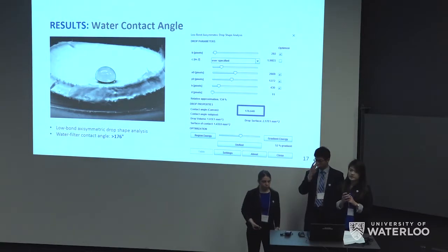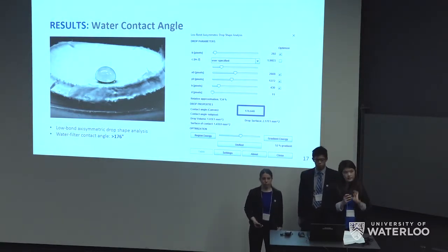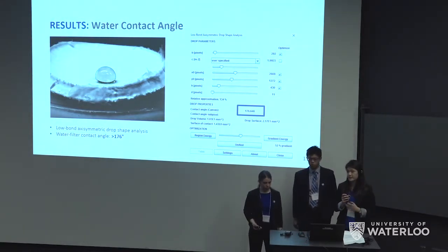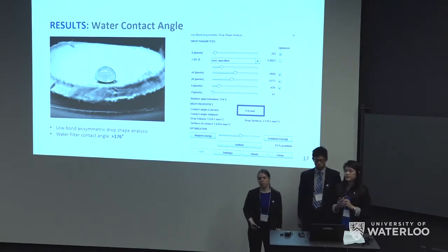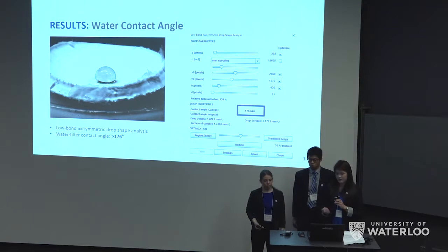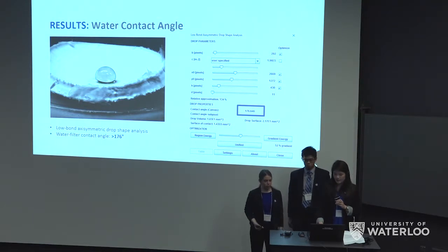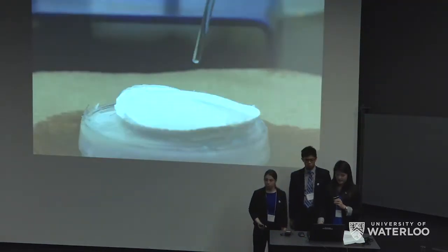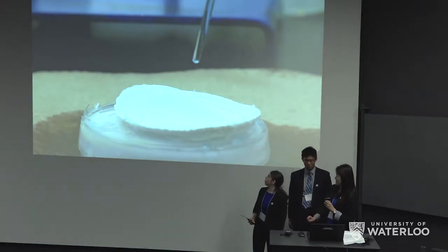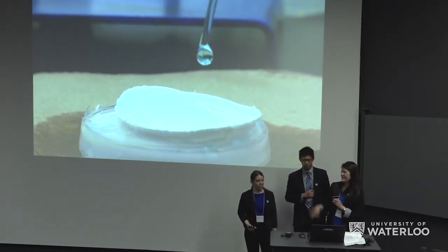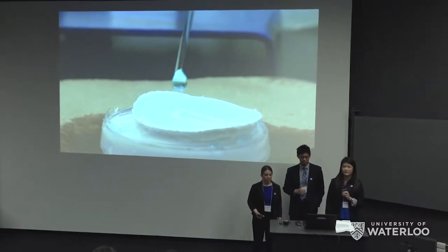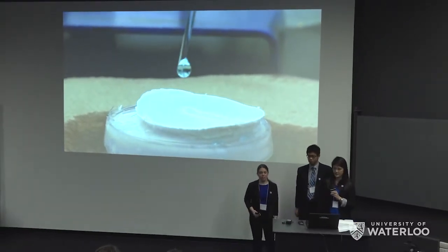Next, we obviously wanted to confirm that our material was superhydrophobic and superoleophilic. So we did a number of contact angle tests. With the water contact angle, we found that it was greater than 176, which is quite impressive. To further illustrate this, if this video would load. Oh, there we go. It's a little bit laggy, but that's water dyed with methylene blue rolling off of the surface.